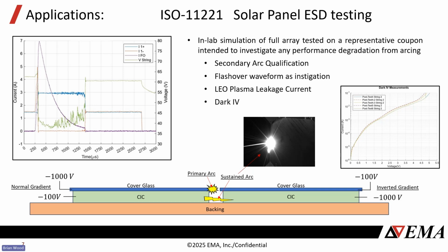And so that's another test that we can do, where essentially you're just kind of trying to operate or bias the coupon at typical voltage levels, and then you can tweak the current densities that you're exposing it to see what leakage levels you're getting and what densities would result in sort of compromising leakage levels.